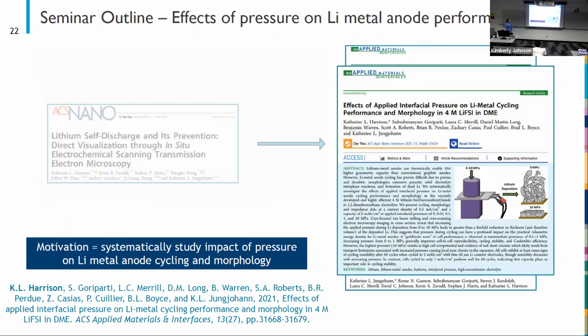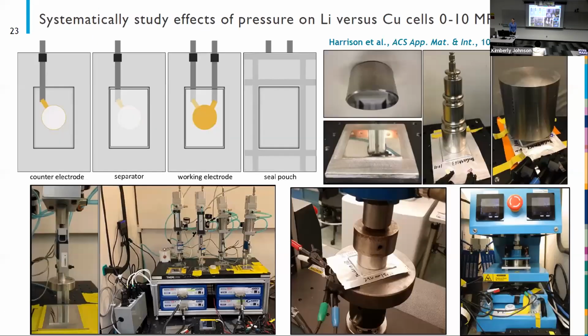So what we set out to do is a systematic study where we look at the effects of pressure over various ranges and try to figure out what the impact is as we vary the pressure intentionally. That led to the paper that is outlined here. So we built pouch cells for this study because pouch cells are easy to apply pressure to, whereas with a coin cell, it's much more difficult to control the pressure.